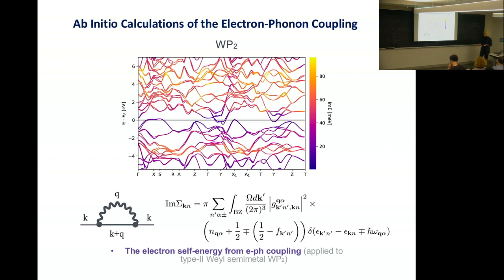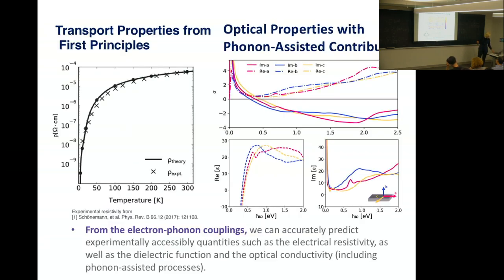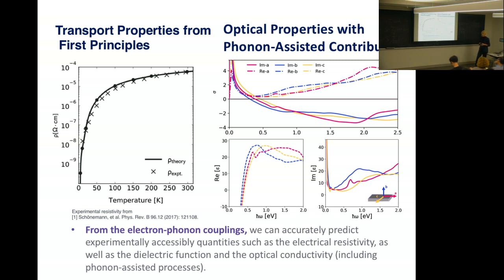This is part of the set of diagrams we include for the electron self-energy calculated from electron-phonon coupling. We also calculate the inverse process — the phonon self-energy — so we think about how electrons dress the phonons and how phonons impact the electrons. We calculate both to get the transport behavior. The plot on the left made me really happy: the solid line is theory, the x's are experiment, no fitting parameter, no fudge parameter, no adjustment. Something was computed, something was measured, they were overlaid and lined up really well. We were encouraged because the way we're describing transport in Weyl semimetals is in fact a quantitative description.